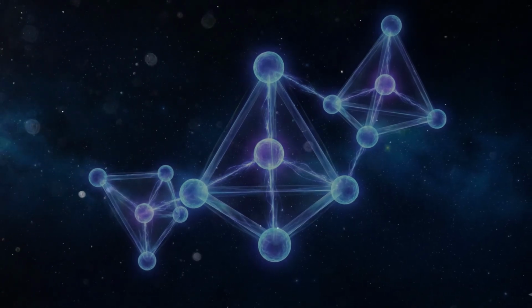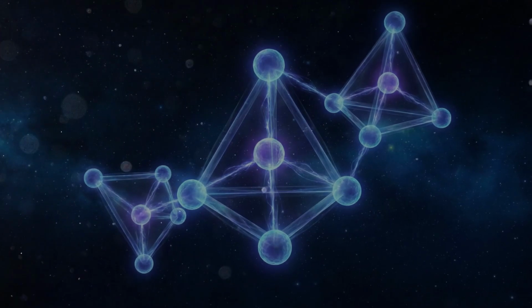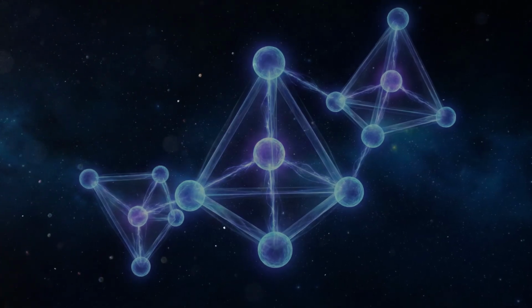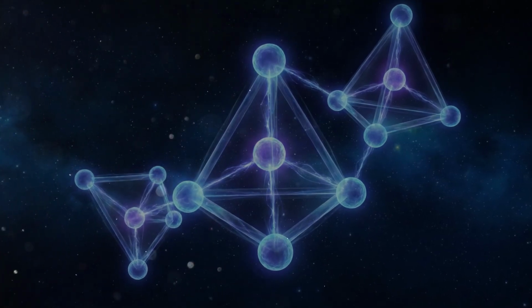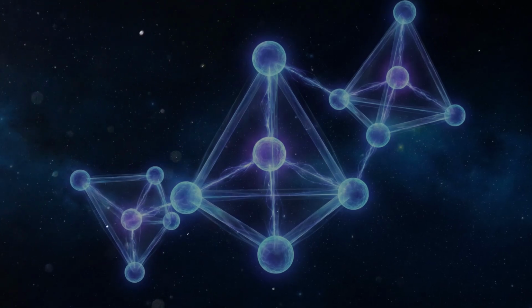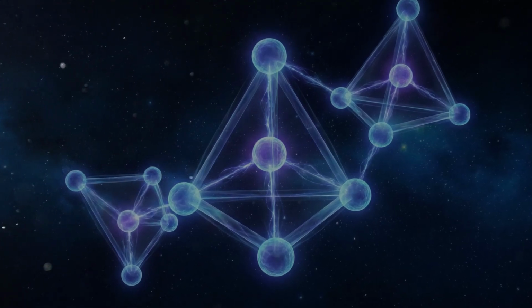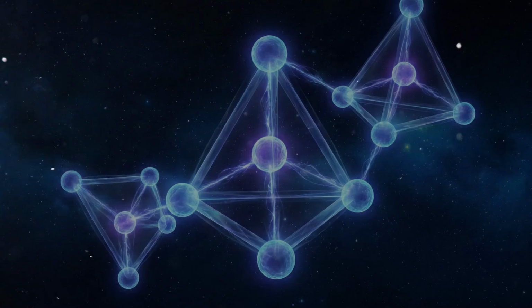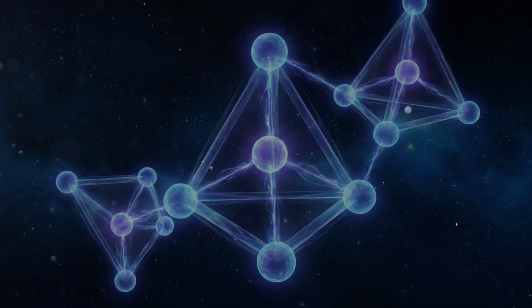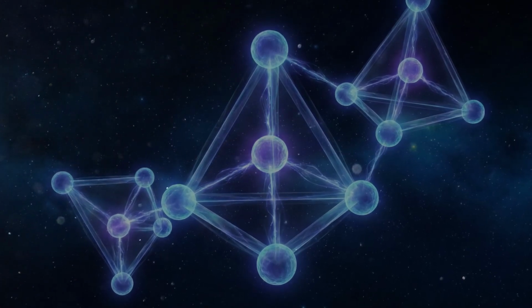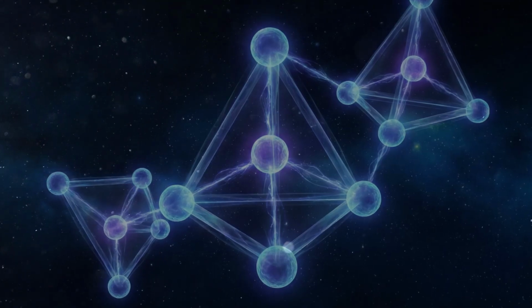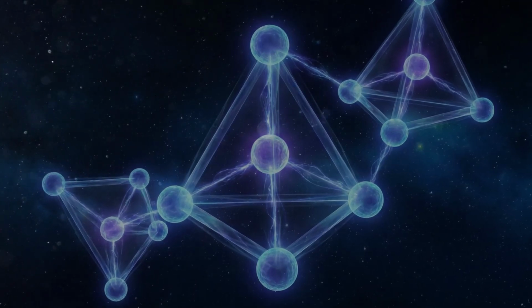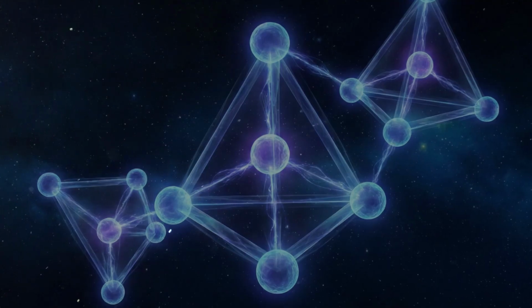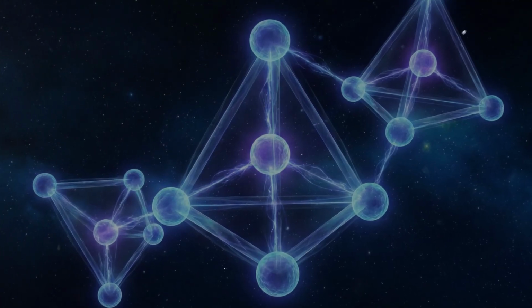Well-formed crystals typically contain more than 99.5% SiO2. But for high-technology applications, even this isn't pure enough. Semiconductor-grade high-purity quartz must contain less than 50 parts per million of impurity elements. At these purity levels, quartz commands prices around $10,000 per ton, a far cry from ordinary sand.